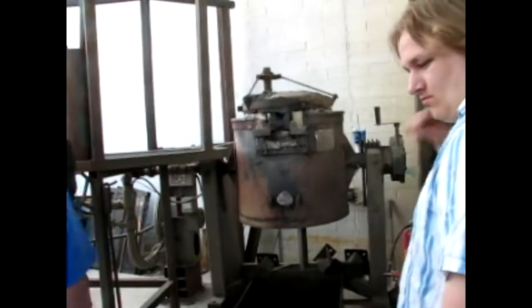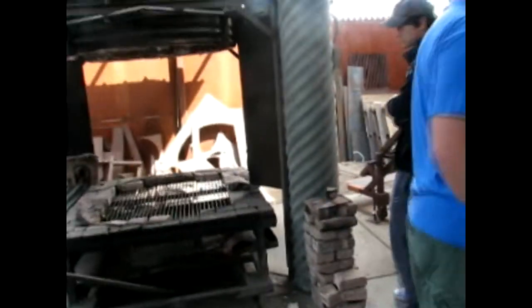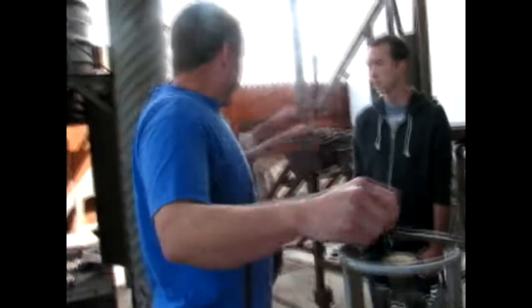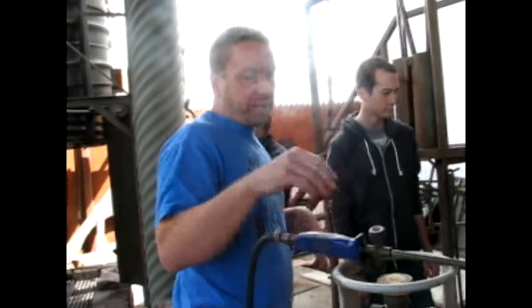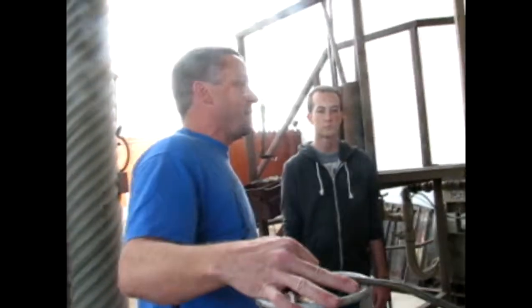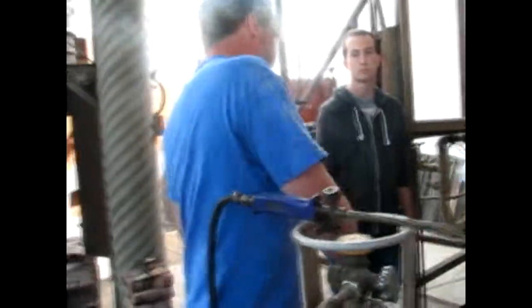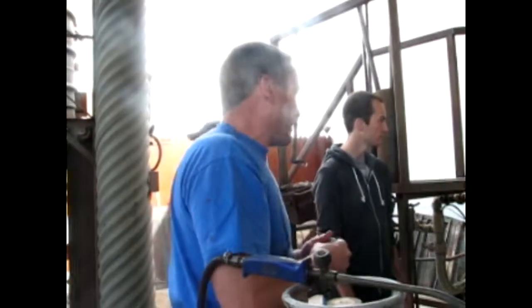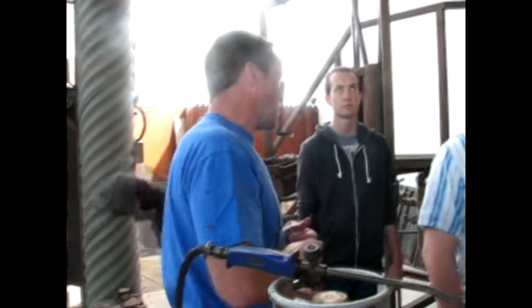And so when it comes time to pour, we fill in the grate with bricks, and then we have to preheat those shells because of the thermal difference. After we burn them out, we let them cool off and then check them because we can repair cracks at that point. And then on pour day, we have to preheat them back up to 1,800 degrees or so, and then we pour the bronze at a little over 2,000.